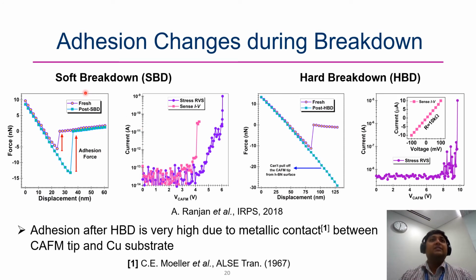So what we see here is that compared to the fresh, unstressed sample and the soft breakdown, yes, the adhesion has changed a bit. But with respect to the hard breakdown, the adhesion was just too huge, and we could not pull the tip off the surface for a displacement of say 125 nanometer. Also, the electrical data shows that in the soft breakdown condition, the dielectric is still insulating, although slightly degraded. So we have a lot of defects nearby, and you can see that there is an increase in conductivity, and also an increase in the adhesion as well.